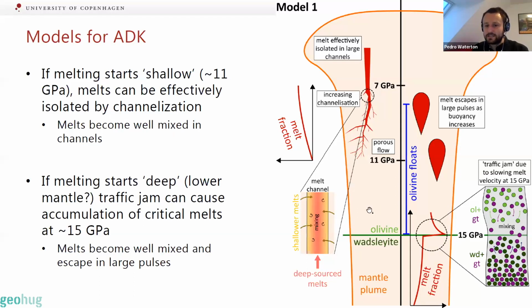The alternative model is that if the melting did start very deep, potentially in the lower mantle or below the transition zone, then as the melt fraction increases and we hit the olivine-wadsleyite boundary, we get this traffic jam effect. So there's a massive increase in porosity as the density difference decreases, and we get a huge spike in melt fraction. And then the idea here is that as this density difference increases again past the transition, the melt would escape as these large pulses. And then these are, again, effectively isolated from the surrounding mantle.